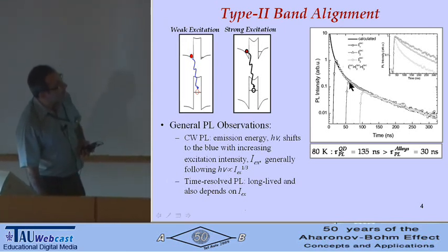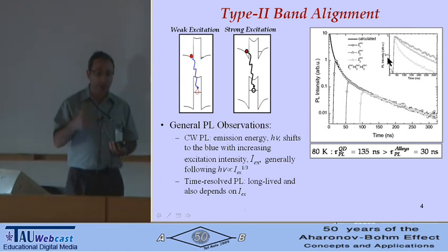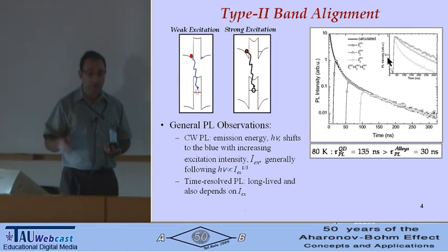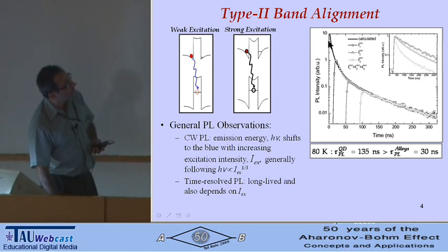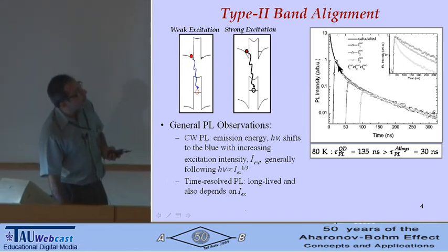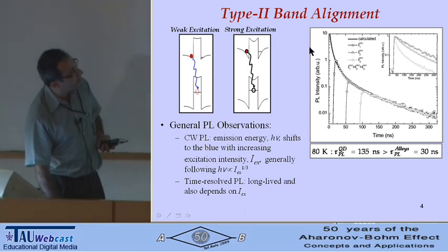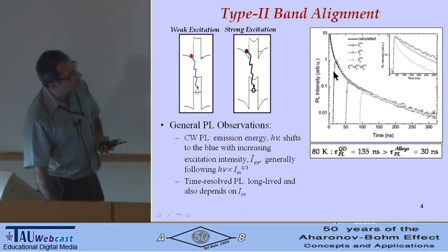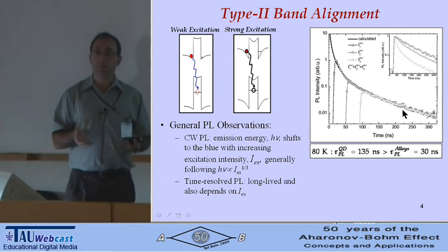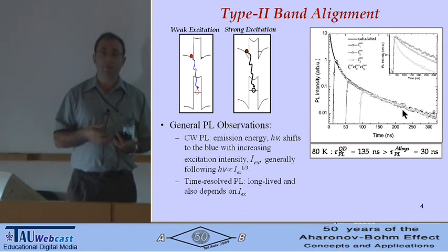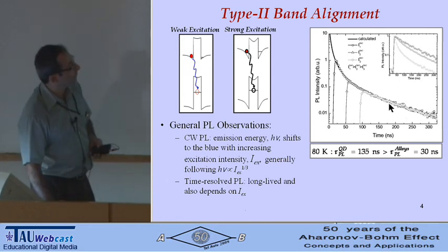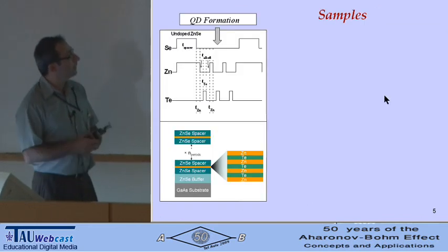And again, time decay changes with excitation. When you pump hard, it's relatively fast. When you pump weaker, it gets slower, and at very weak pumping, it's very, very slow. And because this change is due to the concentration of photogenerated carriers, these three curves have to lie on one master curve, and this is the theoretical calculation, the solid curve, and they all lie on the master curve. So that's the basic idea of the type 2 band alignment, be it for quantum dots or quantum wells or quantum wires.